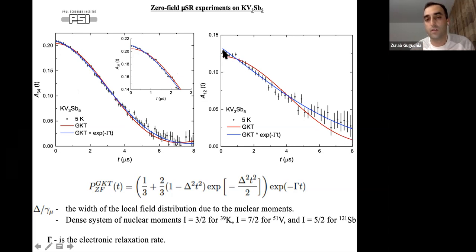and there's a big discrepancy if you look at the data from these forward-backward detectors. So it's clearly this response is anisotropic. And so you need to add an additional exponential relaxation rate, which we suggest is an electronic relaxation rate. So this extra exponent has an electronic origin, which is also supported by the high field measurements. We tried different functions, giving a somewhat more complicated nuclear response, but we always get the additional electronic relaxation rate.